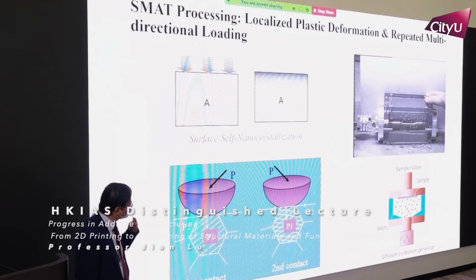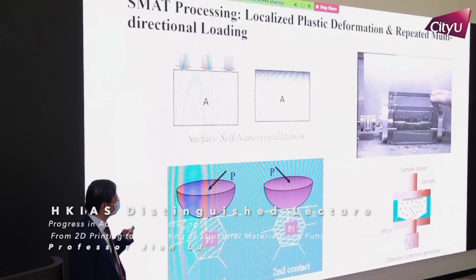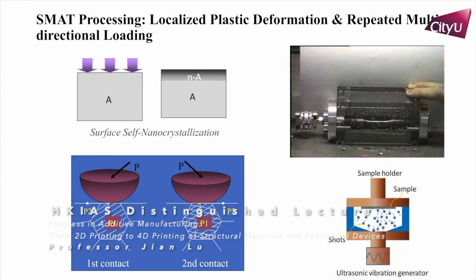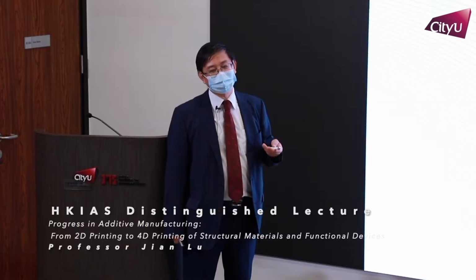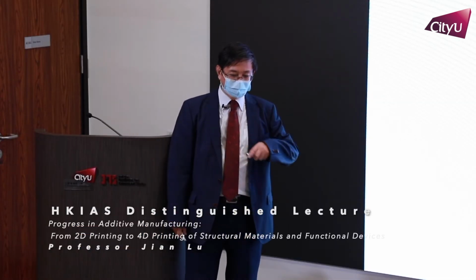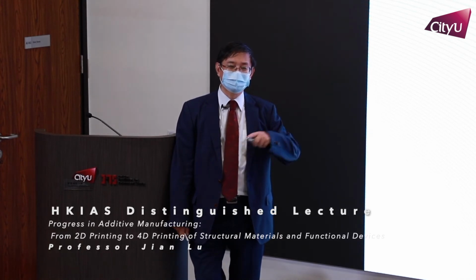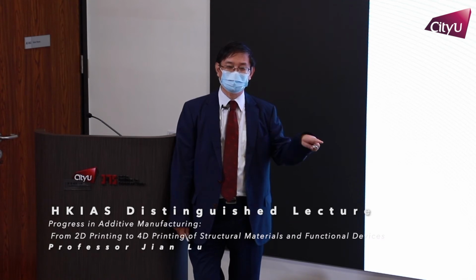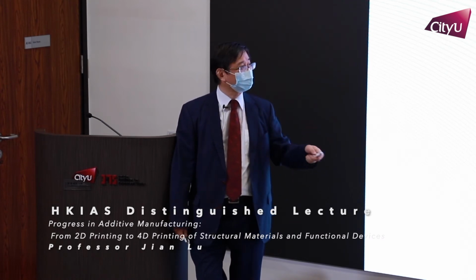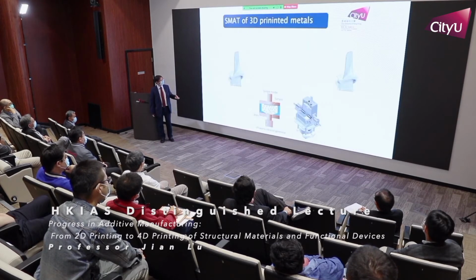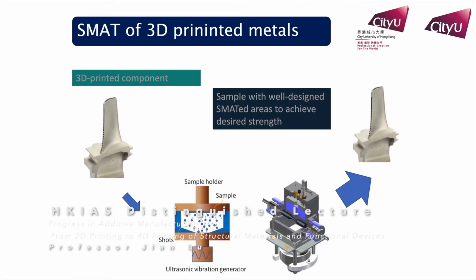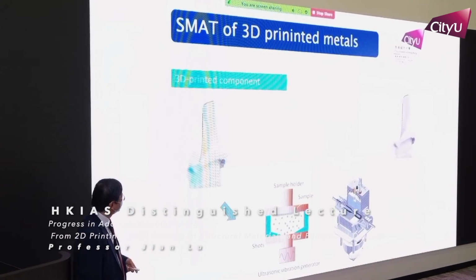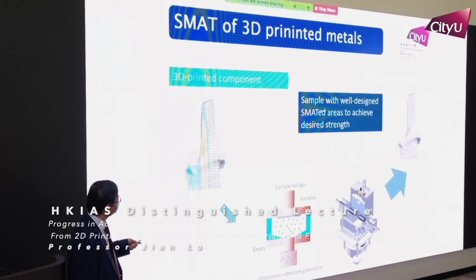And we also use this technology to enhance the mechanical property of 3D printed structure. The major problem of 3D printed structure today is the fatigue life, because of the heterogeneity of the temperature during the laser sintering or other type of high energy sintering. It's very difficult to control. But using this homogenization technique, the surface mechanical attrition, we have done this on the fatigue sample, and we will see the sample with a well-designed SMAT area to achieve desired strength.